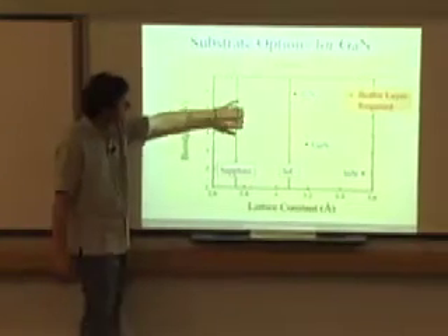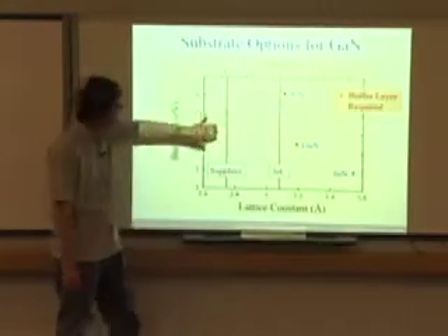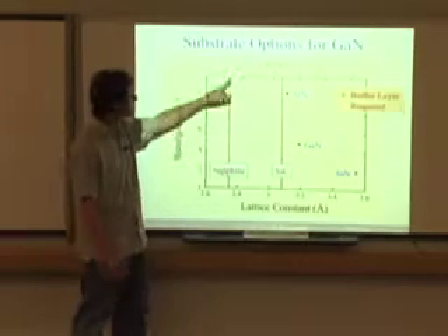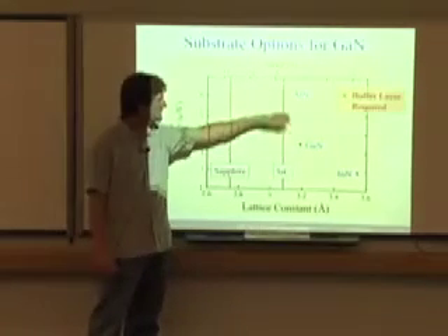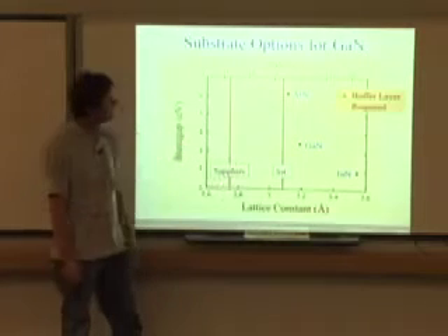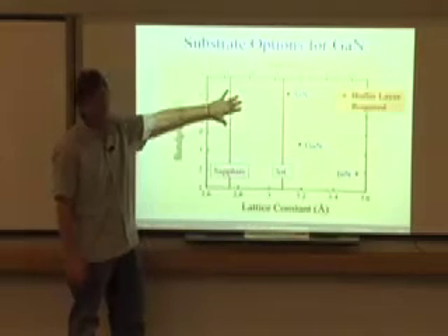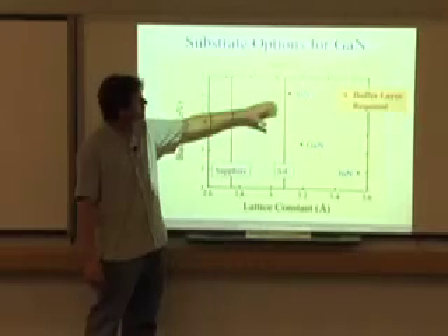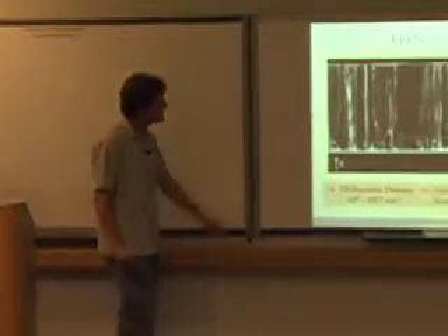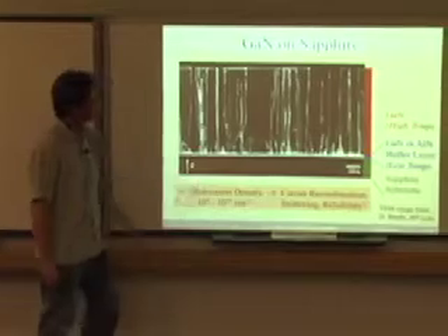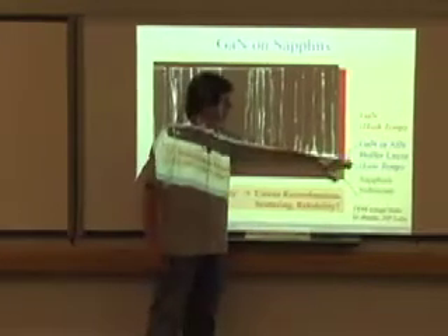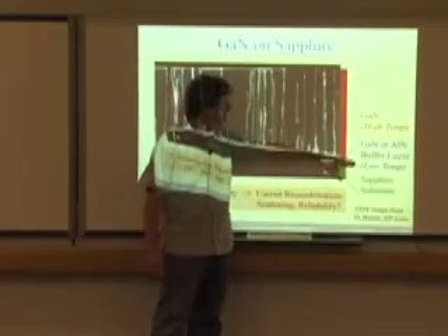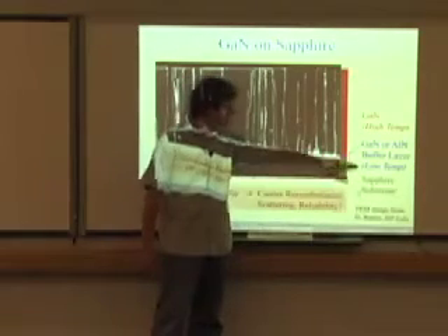When you go to gallium nitride, you have sapphire and silicon carbide. And both of these are heavily mismatched from gallium nitride. Sapphire in particular, I put close to 14%. Silicon carbide is a little better than that, about 3 to 4%. But both, with this extreme lattice mismatch, required a buffer layer to be grown in between the gallium nitride and the sapphire. And so this is an example of gallium nitride growth on sapphire. So when you're growing on sapphire, you needed a low temperature buffer layer, which was developed both by Amano as well as Nakamura.